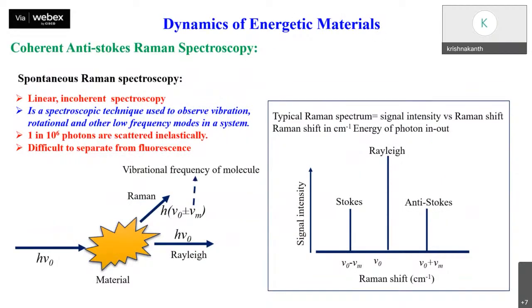And later we have set up a CARS experiment to study the IVR dynamics, intramolecular vibrational redistribution dynamics, of energetic materials, since energetic materials tend to decompose quickly, on the order of picosecond to nanosecond time scale. In the case of conventional spontaneous Raman, it is a linear and incoherent spectroscopy with very weak scattering. One in a million photons will be scattered inelastically, and in the case of fluorescence background, it is very difficult to separate the Raman signal. The picture below shows the Raman process and the typical Raman spectrum.